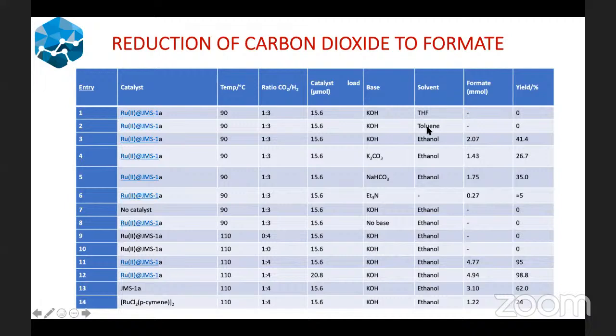And again, we also looked at toluene. There is no product that is formed. And of course, the moment you have ethanol as a solvent during your catalysis, this is when we start to form some product. You can see that here we have 2.07 millimoles of formate being produced, corresponding to 41.4% of the product.